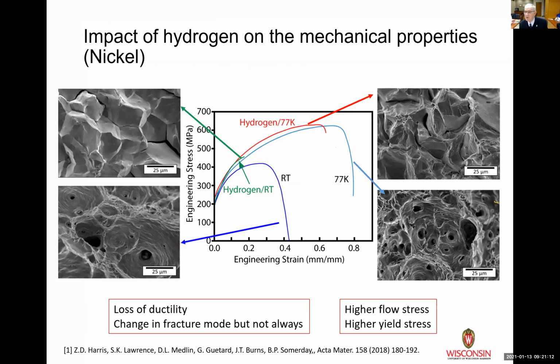Let me turn to an example where we have put hydrogen in and just ask what happens to the material when we put hydrogen in it. Again, a very classic example. It's just putting hydrogen into pure nickel and looking at how putting hydrogen into the nickel impacts the engineering stress versus the engineering strain curve. And all of you have studied hydrogen embrittlement. You'd say, well, this is absolutely obvious. You're going to get a reduction in the ductility. You'll see that there's a higher flow strength with the presence of hydrogen, and it fails quicker.